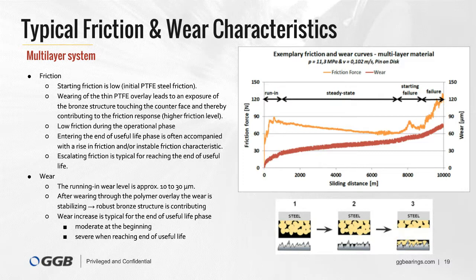This phase is often followed by a fluctuating friction characteristic, which we can explain by an ongoing running-in process, including the establishment of a bronze-PTFE containing transfer film. Usually after that we have a steady-state friction phase, which we can also call the operational performing window of this material. With progress in covered sliding distance, we see a clear change again in the friction characteristic: an increase in friction, and an unstable friction characteristic. Both are indicators that the system starts to enter its end of useful life.